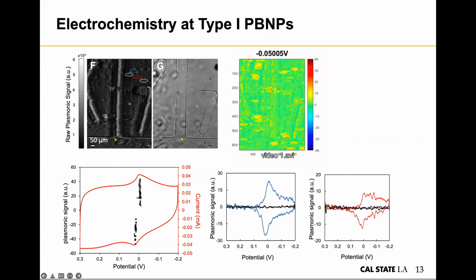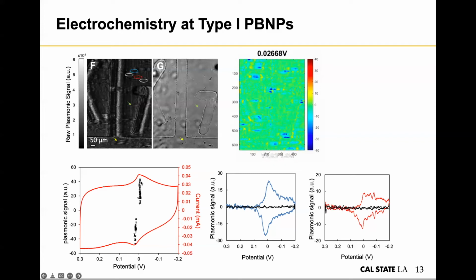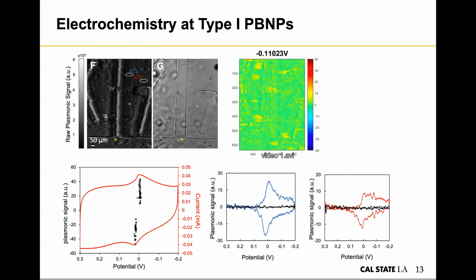position correlates very well with the potentiostat CV, demonstrating that we are observing the electrochemistry of Prussian blue nanoparticles. And we got a wide range of intensity distribution, which can give us information on the size or the activity of different particles. So this is type 1. It's very straightforward. We got what we expected.